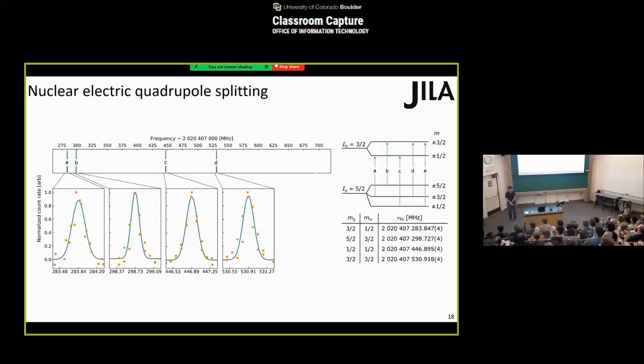Yes, partly. Actually, thorium fluoride is easy to evaporate because its evaporation point is relatively low, or its vapor pressure is relatively high. Also, if you look at the transparency of different materials, you find that mostly fluorides are transparent in the vacuum ultraviolet region. So we decided to try out thorium fluoride. Later we found literature saying that thorium fluoride should indeed be transparent at this VUV frequency. Other thorium materials are harder to produce and not transparent at this wavelength. So thorium fluoride is kind of a natural choice.